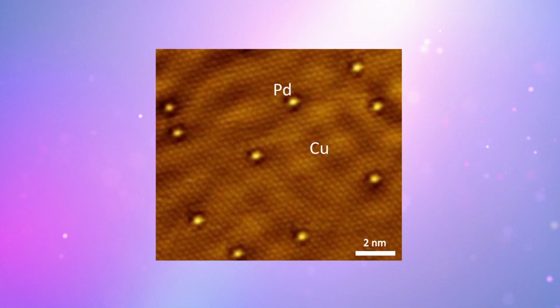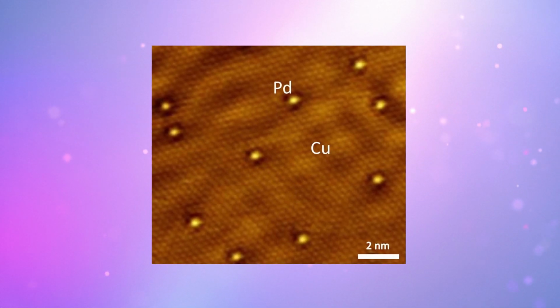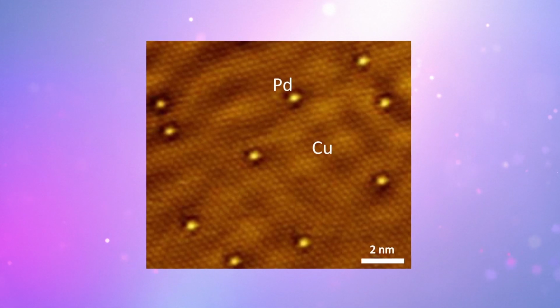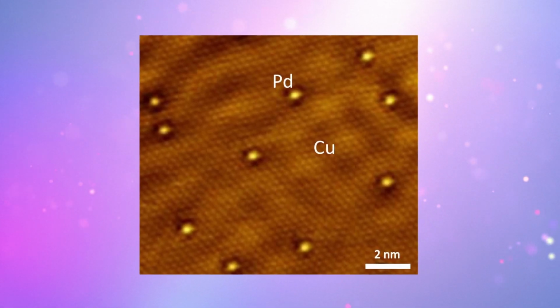And a real sort of lucky discovery came when we were imaging palladium atoms in copper at 5 Kelvin, and suddenly all these little depressions appeared on the image that were skating around on the surface. And I knew instantly from Wilson Ho's earlier work that that was hydrogen atoms. So I also knew that copper cannot dissociate hydrogen. And I also knew that there were only individual palladium atoms in this surface, so it must be that just individual palladium atoms in the copper surface could dissociate and spill over that hydrogen onto the copper surface.